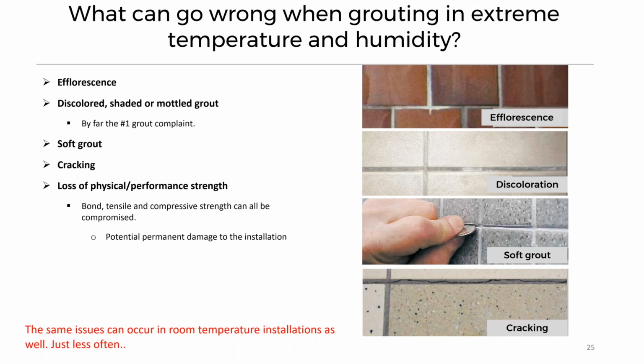Soft or cracking grout can happen by underwatering or overwatering during either the mixing process for cementitious grouts or the cleaning process for any of those grouts. So that's something that distorts the ratio of cement to water. If you play with that, that can cause issues with the W to C ratio, and can cause issues with performance properties. All of those can be compromised: compressive strength, tensile, flexural, or bond strength.